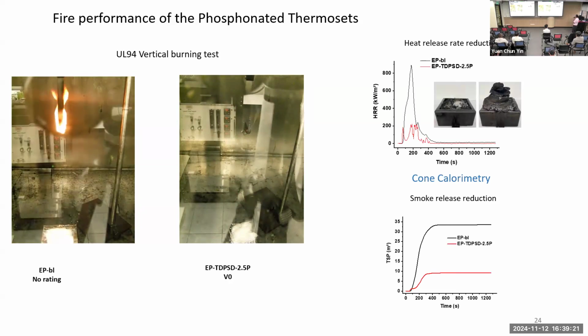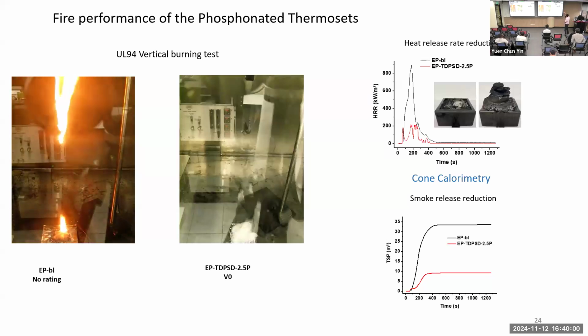Further, when you do a cone calorimeter test, you can see the amount of heat produced is quite low. The new polymer or the network also produces a lot of char and inhibits the burning process. Okay, so what is very interesting is, unlike many flame retardant systems, this system produces less smoke as well. When you work with flame retardant materials, normally you also increase the smoke. That's a normal side effect of a flame retardant. But in our case, the fact that we produce a lot of char, we reduce the smoke, I would say.